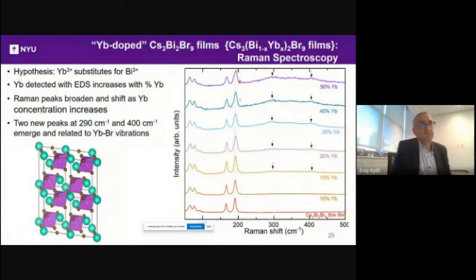There is also a shift in the Raman, as you would expect. They broaden and shift as ytterbium 3+ substitutes for bismuth 3+. I'm going to go a little bit faster to make up for the time that we lost at the beginning, so that I can get to some of the results. And then, as you start putting in ytterbium, you start getting these broad peaks, which we think are due to ytterbium-bromine vibrations. It's small, but it is there, detectable.